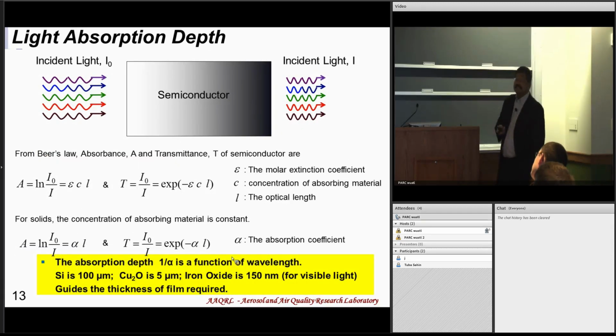The other thing is how thick should this material be, or how thick should my device be. Of course, you don't want the light to just come in and get through. And a simple Beer-Lambert's law expression could then, using the absorption coefficient, be used to calculate what we call an absorption depth. So I just use as a characteristic length 1 over alpha, the inverse of the absorption coefficient. This is of course a function of the wavelength, so you can do these calculations, and you can see that this would guide the thickness of the film that I require.